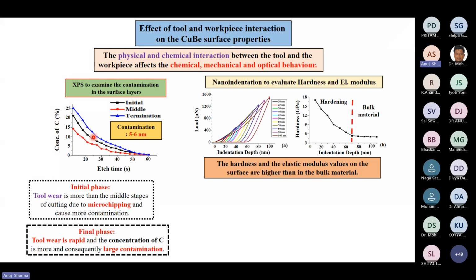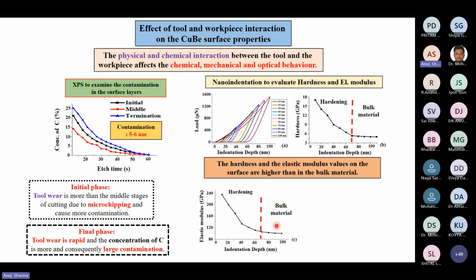Similarly, nanoindentation was carried out to evaluate the hardness and elastic modulus at different depths from the top of the surface. It showed that at the top surface layer, a hardened layer was observed, but in the bulk layer the hardness is the same. On the top layer, which is around 60 to 70 nanometers, hardening is taking place. That is due to residual stresses on the surface from the compressive stresses from the tool. Similarly, the same thing was shown in the elastic modulus graph.